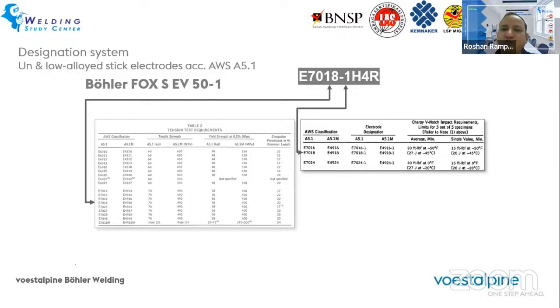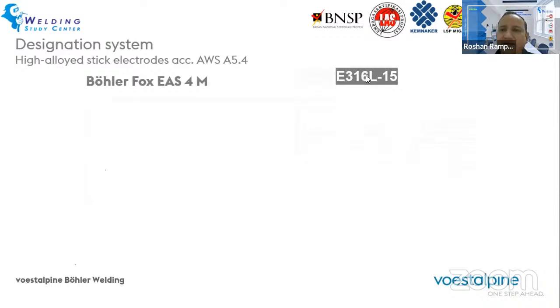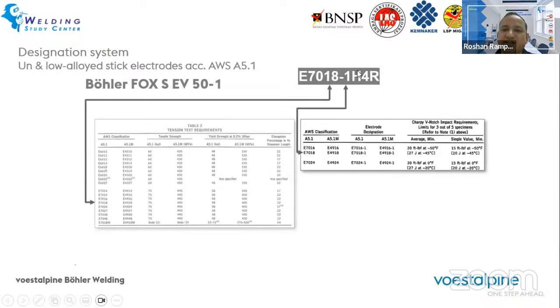In a similar way, H4R indicates that H4 is the diffusible hydrogen level, meaning this electrode is designed to meet the requirement of diffusible hydrogen level less than 4 ml per 100 gram of weld deposit. And R indicates that the coating itself is a moisture resistant coating, so the moisture content in the coating is less than 0.15%. In that case, it can be classified as H4R classification. So the total classification is E7018-1H4R. So this completely indicates the mechanical properties, impact properties, diffusible hydrogen level, coating type. It gives you the full picture of what this electrode is capable of and what type of electrode it is.